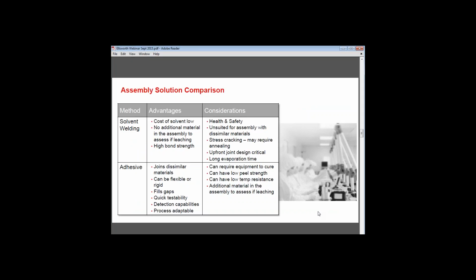Thanks. So as Tom stated, primarily the method of choice and the method that's been tried and true for many, many years is solvent welding or solvent bonding. And for good reason. It's a very low cost material in and of itself. There's no additional material in the assembly to worry about looking for or assessing if that material is leaching, because the solvent will evaporate and be dismissed from the bond line, and typically always results in a pretty high bond strength, especially with tubing assemblies.